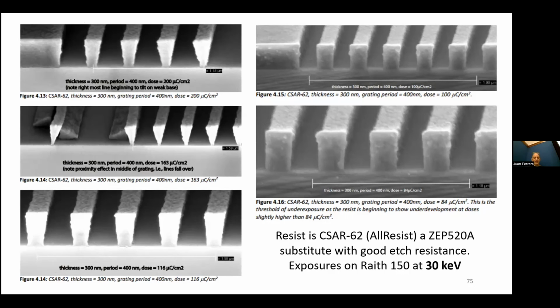We're getting a little bit short on time if people want to ask questions, but I still really want to show this. This is some work that Juan did with Hank Smith at a startup company of his when we first started evaluating CSAR resist, which is similar to ZEP. And there are these beautiful cross sections. And what I want to point out is this stuff was done at 30 kV, and you get some undercut. 30 kV is really great in some ways because you get undercut if you're doing liftoff, that's helpful. And if you do more, it starts to really get undercut and you get very little holding the line in place, or maybe you get this.